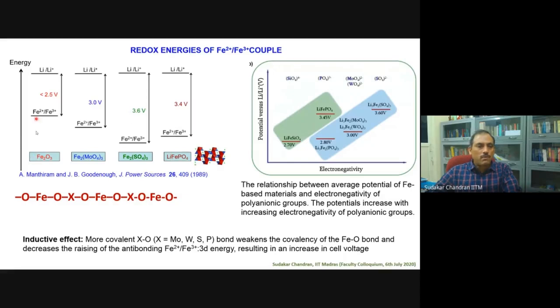Here, pictorially, it is shown Fe2O3 has less than 2.5 volt. The moment you put molybdenum or tungsten, it is 3 volt. Sulfate, it's 3.6. And they explain this based on the inductive effect. In this particular Nasicon structure, the iron, oxygen, the molybdenum, oxygen, iron, they are connected well because of the structural connection they have. The molybdenum-oxygen bonding is highly covalent, and that weakens the covalency of the Fe-O bond. In other words, the electronegativity changes if you change the polyanions. As the electronegativity increases, it pushes the Fe2+/Fe3+ redox energy level down, which results in an increase in the cell voltage.